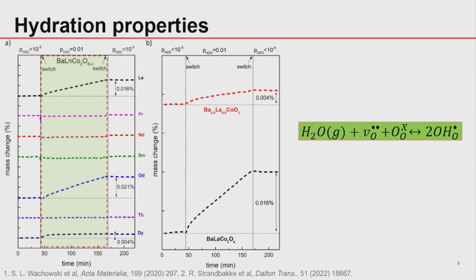Now, when we compare the simple perovskites with the double perovskite, what we see is that barium lanthanum cobalt oxide, which is a double perovskite, showed the highest weight gain, of around 0.016%, versus BLC, which is a simple cubic perovskite, and showed only a weight gain of 0.004%. So this indicates that a double perovskite, which has a high amount of oxide vacancies, leads to high hydration. So if we use double perovskite in electrochemical performance, they should show a better performance compared to BLC.